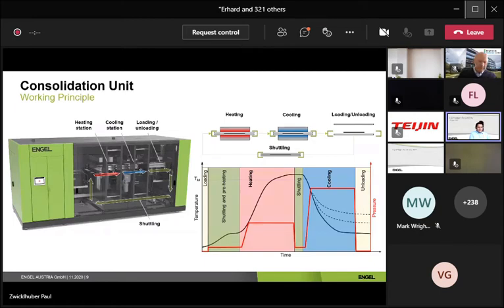The graph on the right shows the temperature curve in black and the pressure curve in red over the cycle time. In the heating station, the tape stack is heated up under low pressure. When the target temperature has been reached, the stack is transported to the cooling station and cooled down under higher pressure.